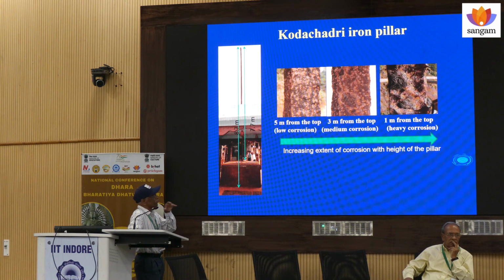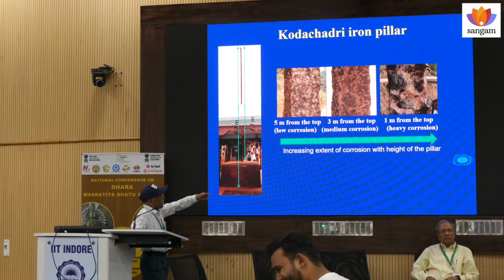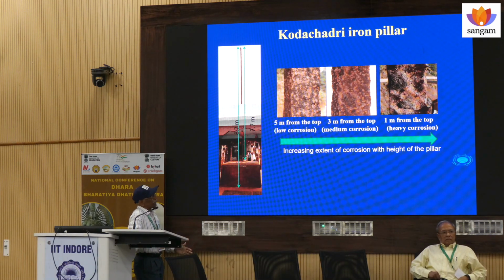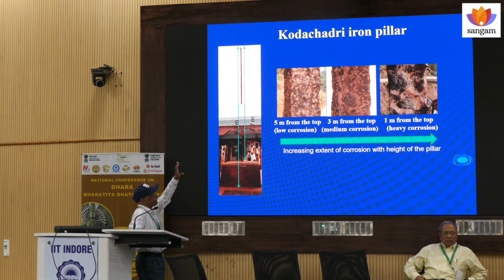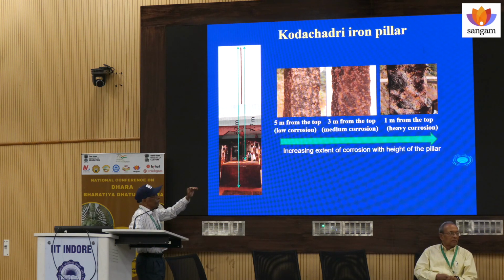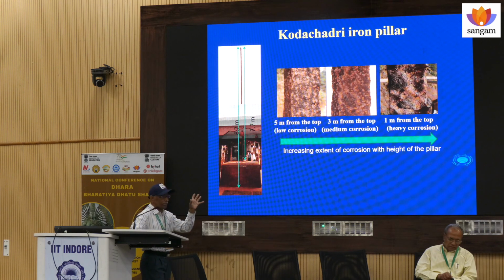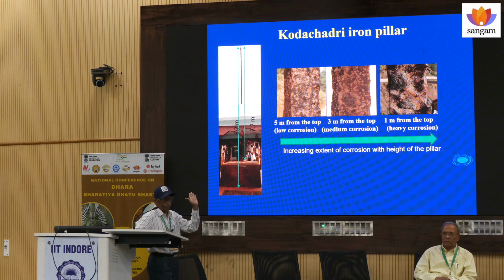This cross section is relatively small, and we have taken some studies here also from different portions. And then if you see, the corrosion rate varies from bottom to top. In the top region, the corrosion is very high, whereas as you come down, the corrosion rate is low. Another point is, this pillar has a square cross section, and the side which is exposed to the Arabian Sea, the west side, has the highest corrosion, whereas the face on the eastern side has almost very small corrosion.